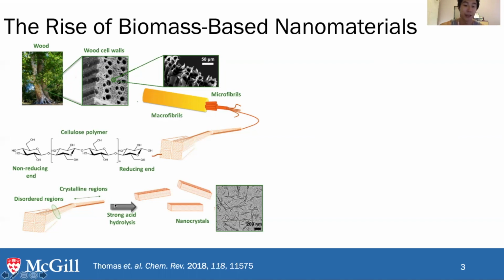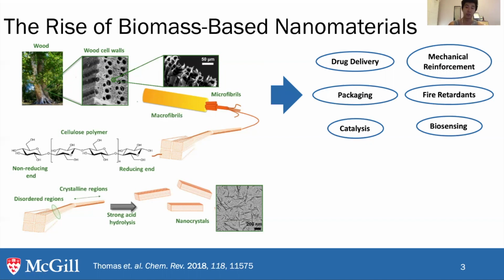If we use acid hydrolysis, the acid attacks the disordered regions and depolymerizes them while keeping the crystalline regions intact. So they make these crystals on the nanoscale, with a high aspect ratio, around 200 nanometers in length. From this material, a lot of applications have been discovered, as well as commercialization happening at this moment. And our lab specifically focuses on using these as a support for catalysis.